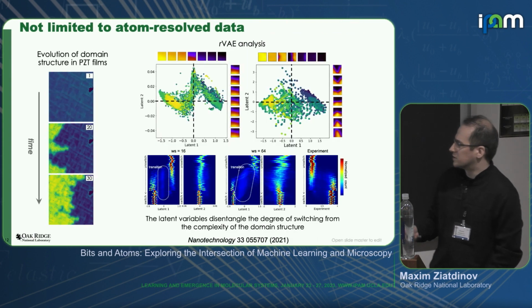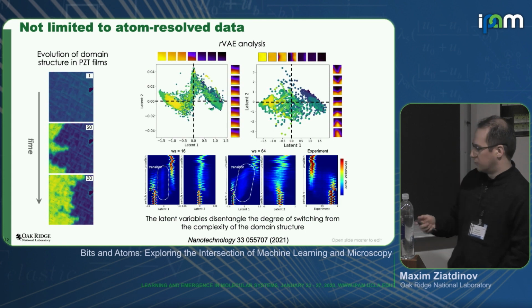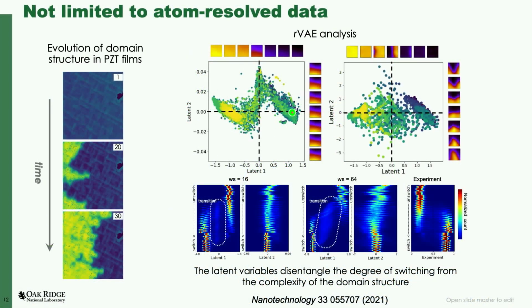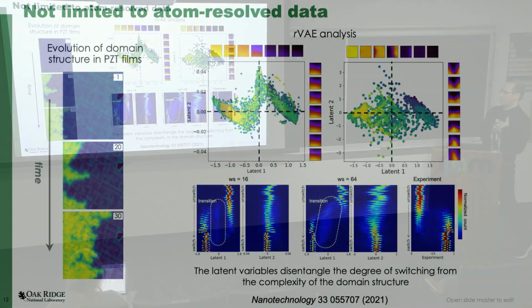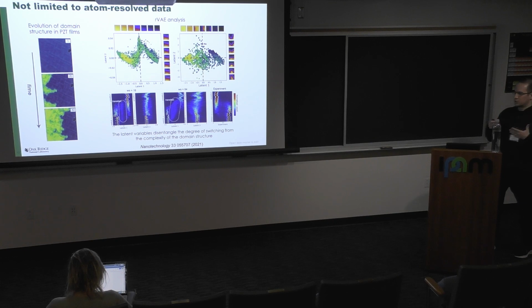And also, it's not limited to atom-resolved data. Here we analyzed a system where we were observing the growth of ferroelectric domains on the surface, and what the variational autoencoder allowed us to do was disentangle the degree of switching from the complexity of the domain structure. And the key part here was that we accounted for rotational invariances, because in this particular experiment, if you take a domain and rotate it by some arbitrary angle, it's still the same physics. So again, we used something that we already know about the system to help us find something that we may not have necessarily known at the time. Right? That's the idea.